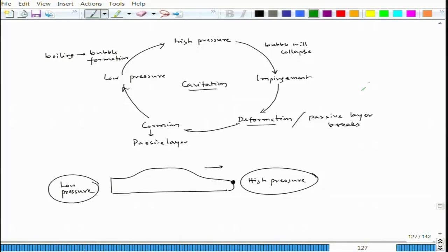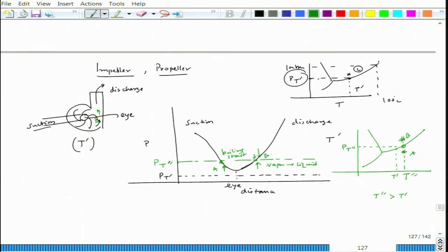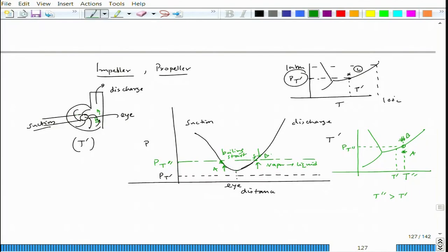So, this is the cycle that would operate there, but actually this is the situation that happens in the case of a pump. The pressure line which corresponds to the boiling of water at that temperature is crossed from suction to the eye, and that crossing led to vapor formation. And when the water is moved away from the eye to the discharge, at one location that pressure line P double prime will be crossed due to high pressure, and those bubbles will collapse because the vapor has to convert to liquid. That happens continuously, because this particular pump will keep on operating and keep on sucking water through the eye and leaving it to the discharge.